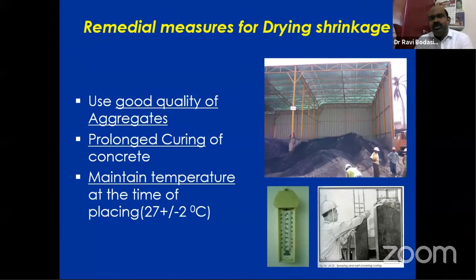So remedial measures are good quality aggregates and prolonged curing for concrete, which is mandatorily done for at least, as the code is saying, minimum 7 to 10 days; the element requires curing. Why? Because as we are assuming the 7 days, it should reach at least 2/3 of the design strength. So at least for a period of 7 to 10 days it requires curing. But even then, within the next 2 to 3 days we are all forced to stop, to take up the next phase of activity. And as I already discussed, the temperature for pouring is 27 plus or minus 2 degrees Celsius.